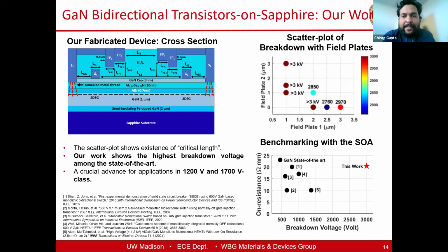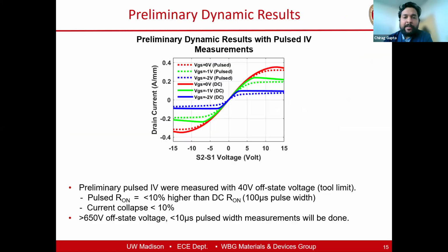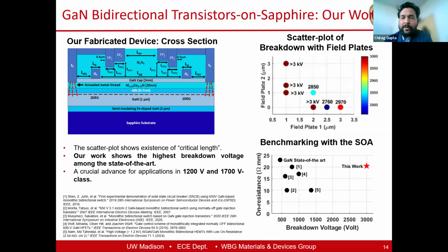So this is one of the highest breakdown voltage transistors for bidirectional devices that is available at the moment. And of course, with 3 kilovolt, it helps to expand this to 1200 volt or 1700 volt applications as well. The on resistance was quite good. We got somewhere close to 10 milliohm centimeter square, which is quite a good number for gallium nitride transistors going close to 3 kilovolt.